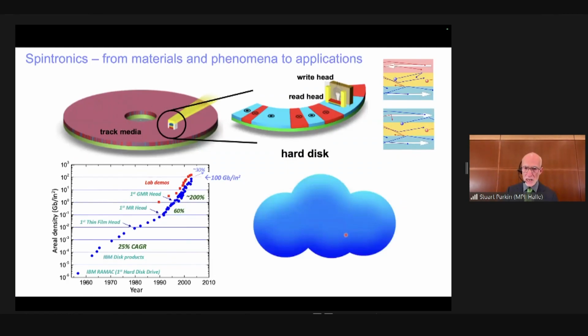So what does this mean? If we now introduce this spin valve sensing device into a magnetic disk drive, and this happened in 1997 by IBM, where I worked at the time, this enabled the numbers of magnetic regions, or the bits per unit area in a magnetic disk drive, to increase dramatically faster than was possible before. And this is shown in the bottom left picture of how the areal density, the numbers of gigabits that could be stored per square inch in a magnetic film, in a magnetic disk drive, evolved as a function of time.